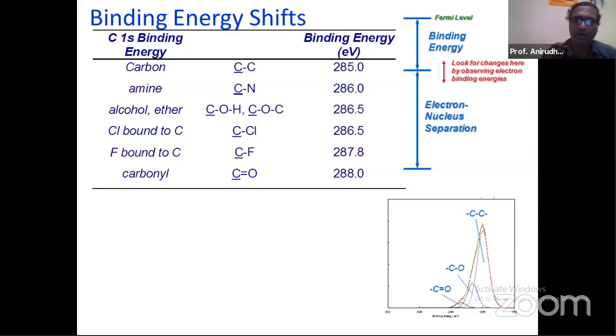Now your idea is to confirm the presence of those materials on the interface by using XPS, and then you can form some kind of an idea, though it cannot be complete, because one characterization alone cannot give you the complete details of the chemical coordination, but it will give you some basic information about the coordination related to the different elements in your set. I am just repeating: you would require a very large database so that you can search for the kind of coordination you are expecting between carbon and nitrogen, or carbon and oxygen, carbon and iron, and so on. They are available free of cost on many sites, the most popular being La Surface, lasurface.com. You can just Google it and enter their website.